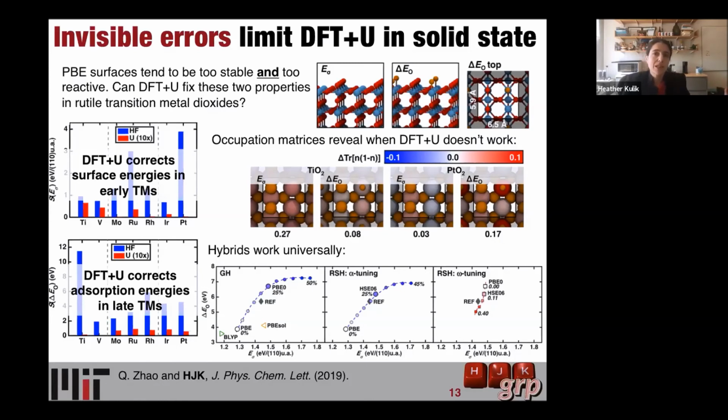That might also relate to some of the questions that came up earlier with V, is a lot of times when these things fail, it's not really the DFT+U method, it's that the construction that we project onto the atomic states and the atomic states tell us about the error in the functional, that's what's failing.